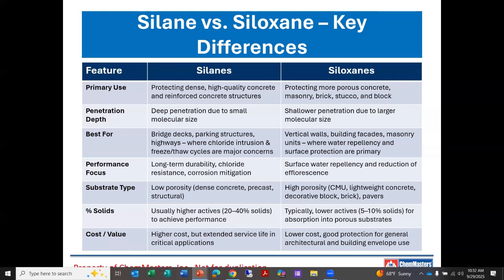The substrate types, again, percent solids. It's not easy to compare these materials by virtue of their percent solids because of the longer and larger molecular size of the siloxane. But you're typically going to see silanes that range from 20 to 40% active solids, and typically siloxanes are in the 5 to 10% area. And of course, sometimes the cost may come into things. Silanes are higher cost. They do have an extended surface life in those critical applications, such as bridge decks and parking structures, whereas the siloxanes are lower cost, but have preferred characteristics in the architectural and building envelope applications.